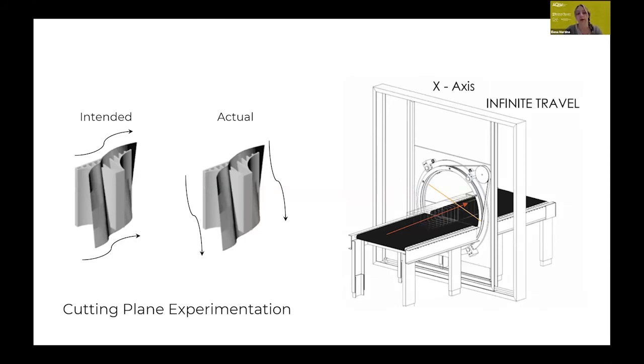The cut to achieve the balance of the exposed webbing and the curved geometry was intended to be executed parallel to the extrusion, so as to cut through each piece of webbing one by one. This was an experimentation of the wire cutter's capabilities to achieve new forms by cutting against the extrusion. But during production, the speed of the wire was affected by cutting through the clay and then void and then clay, and so the outcome did not match the design intentions of the piece.